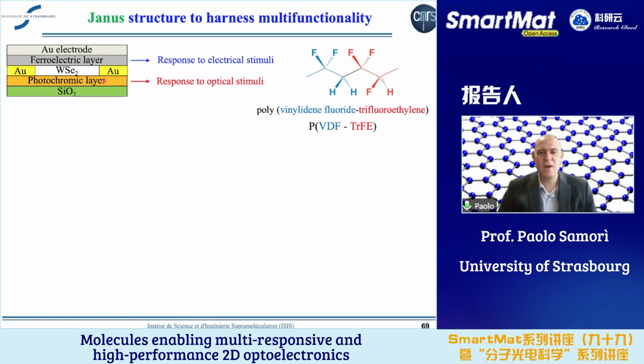And so we make a layer of these materials because the ferroelectric state of the gate insulator layer influences the surface potential of the interface with the semiconductor, and this can be used to control the accumulation or the depletion state of the charge in the device.